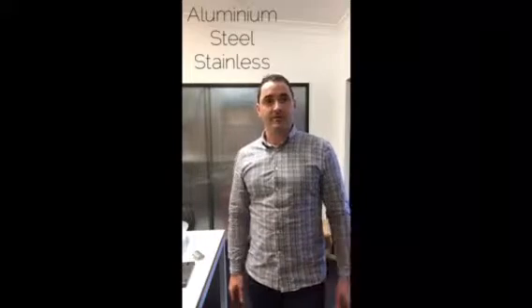If you don't want the rough look of the hot dip galvanized, then we can also do a zinc powder prime. This gives a much smoother finish than gal, but it's nowhere near as durable and isn't going to give us the long corrosion resistance that galvanizing does. With zinc powder priming, it's a powder coating process. We take the raw steel, we sandblast it to get rid of any corroded material that sits on the surface and etch up the material so that we get really good adhesion. We then cover it with a zinc-rich powder primer and then go through the powder coating process where we heat the piece and it fuses on. We then bring it out and then we spray on the top coat colour, and it goes back through the cycle and we get our coloured top coat. Nice smooth finish, but not as durable as hot dip galvanizing.